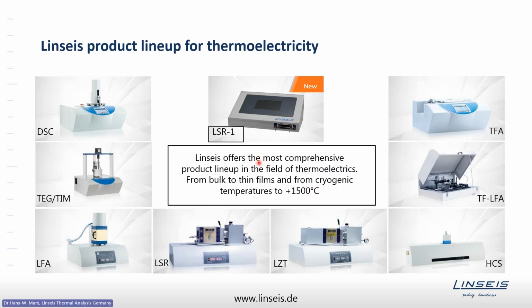So Linseis offers a very broad product lineup for the characterization of thermoelectric materials, for bulk materials, for thin films, and this in the very broad temperature range, from cryogenic temperatures up to plus 1,500 degrees centigrade. The figure of merit depends on temperature, and not only the figure of merit, but also the Seebeck coefficient, the thermal conductivity, and the electric conductivity are all dependent on the actual temperature, so that the characterization has to be done at a defined temperature.